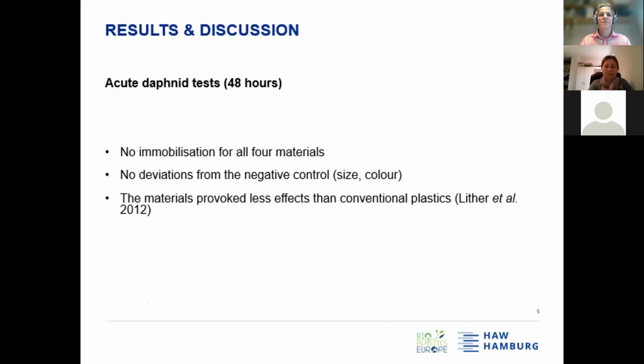So now I would like to explain the results from the daphnid tests. In all acute daphnid tests, we didn't observe any immobilization of the daphnids. So no daphnids died during the 48-hour testing, and also no deviations from the negative control in size and color were observed. Compared to other studies, for example the study of Lithner et al. from 2012, the bioplastic materials provoke less effects towards daphnids than conventional plastics.